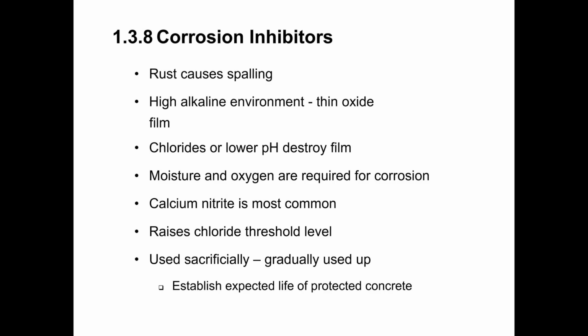You can see this sometimes in a structure. You may have a structure that has been in place for a number of years, never had any issues with corrosion, but then once the corrosion starts, you start seeing signs of corrosion. That corrosion is probably going to accelerate fairly quickly, and this is the reason why. Because as that corrosion advances, it opens up pathways for more moisture and oxygen to reach the reinforcing, which then speeds up the corrosion process. So it's just a vicious cycle once it starts, unless we do something to intervene and to cut off the source of moisture and oxygen and interfere with the corrosion process.